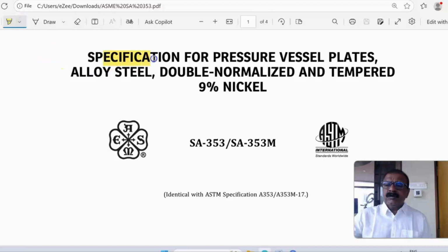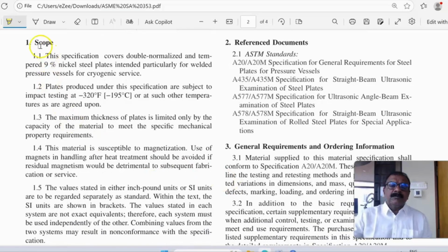This is a specification for pressure vessel plates of alloy steel, double normalized and tempered 9% nickel. And this is identical with ASTM specification A353. Then we go to scope. Scope says this specification covers double normalized and tempered 9% nickel steel plates intended particularly for welded pressure vessels for cryogenic services. Plates produced under this specification are subject to impact testing at minus 195 degrees centigrade or at other temperature agreed upon by purchaser and manufacturer.